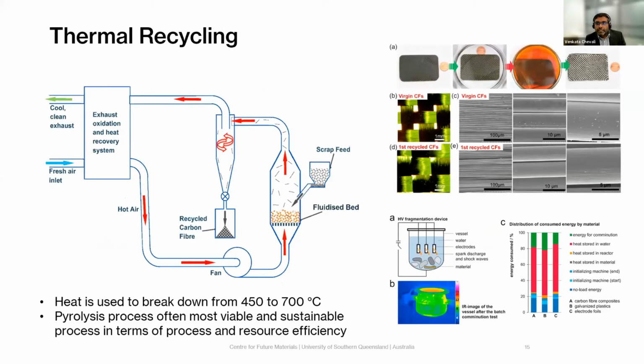being you're using heat. So the heat is from a temperature range of 450 degrees Celsius to 700 degrees Celsius, decomposing all of the resin matrices. So even the high performance thermoplastics or thermosets in that aspect would be completely decomposed at that stage, whereas the breakdown of carbon fiber has not yet begun. So that is, so to speak, a sweet spot where you would like to apply the thermal recycling methods.